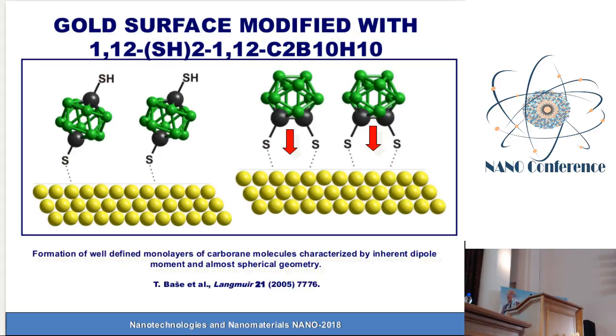Another application of boron clusters is to modify the properties of metal surfaces. The easiest case is to modify the surface of gold nanoparticles with boron clusters containing a thiol function, because of the formation of the stable bond between the sulfur and gold. And again, using different boron clusters with different properties, more or less lipophilic, for example, or containing additional substituents attached to the boron clusters, one can modify the properties of the metal for different applications.